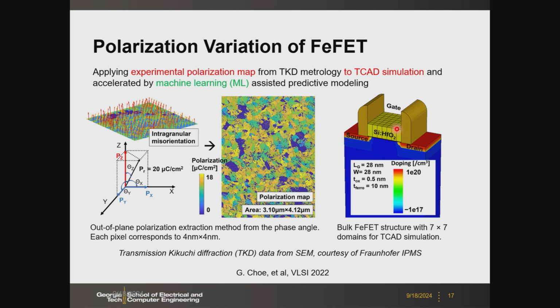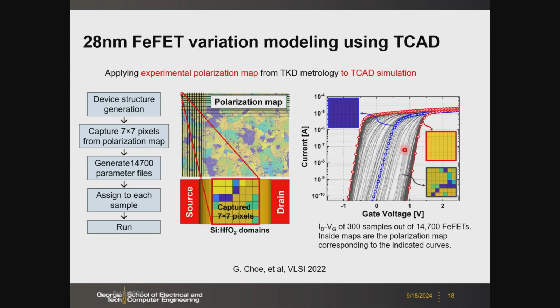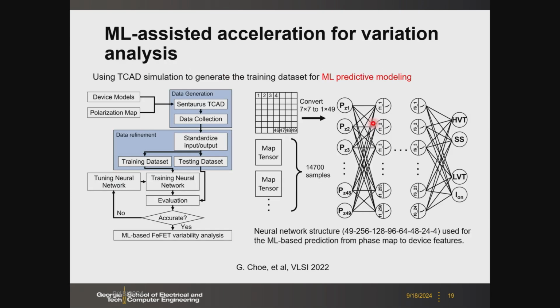Okay. So for example, here we create some TCAD model, and then we treat this polarization variation map as an image classification problem. So if we build the transistor at this location, we may have this kind of polarization map in the gate area, and this could be used as the training data set to run the TCAD, and then we get the corresponding IDVG for this image map. So once we gather enough data, for example 3,000 points of this kind of correlation between the image and the figure of merit of the device, for example the threshold voltage, the subthreshold slope, or the on-state current, then we can train the neural network.